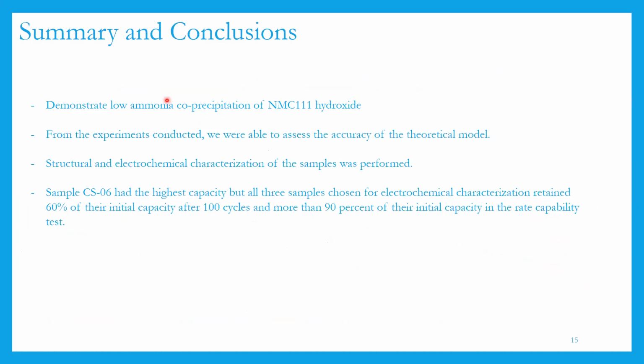And so some of the conclusions we drew from this project: we were able to demonstrate co-precipitation of the NMC111 hydroxide using low ammonia co-precipitation. And then from the experiments conducted, we were able to assess the accuracy of the theoretical model. So for the conditions that we tried, we found that the model was more than 50% accurate. And then we were able to perform structural and electrochemical characterization of the samples. And then also found the sample CS06 had the highest specific capacity. And then all 3 materials were able to retain 60% of their initial capacity after 100 cycles. And they were also able to retain more than 90% of the initial capacity after charging and discharging them at different current rates, and then going back to the lowest C rate.